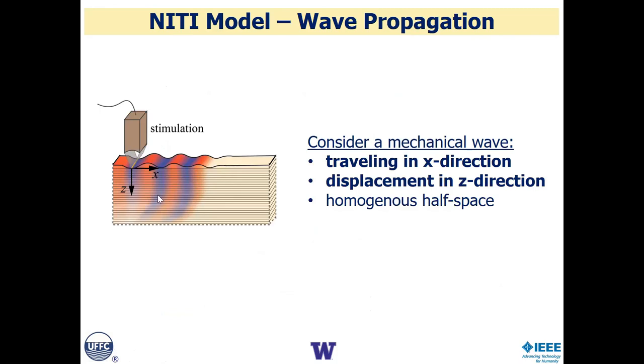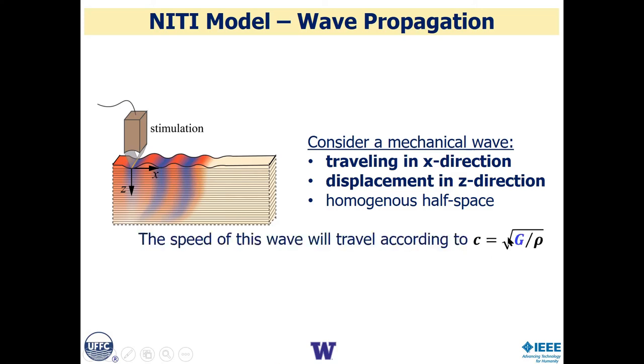We can find the information. However, when we now do this micro-tapping experiment and launch waves into the material and look at the polarization of the transversely propagating waves, we see that the wave speed is directly related to just the G parameter. That's bad because G does not determine tension. Tension determines shape. And so there's minimal relation between those wave speeds and predictions of how shape will change due to an intervention.